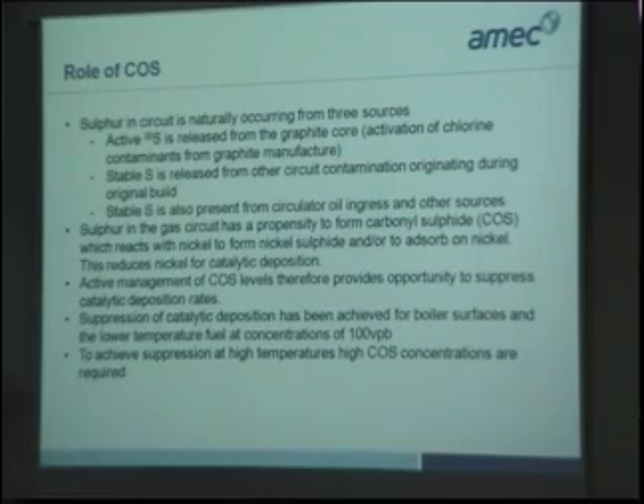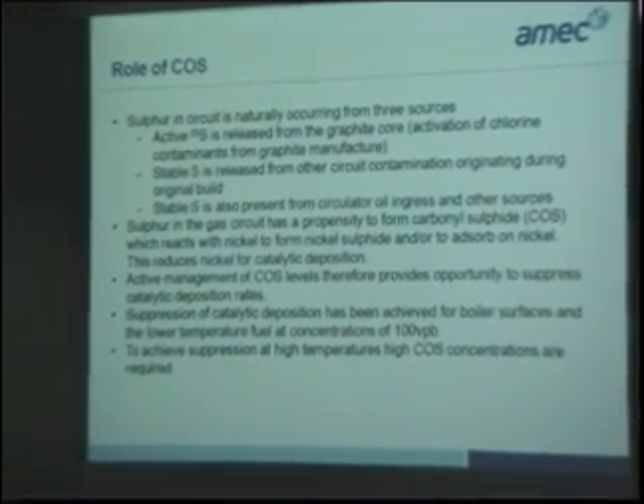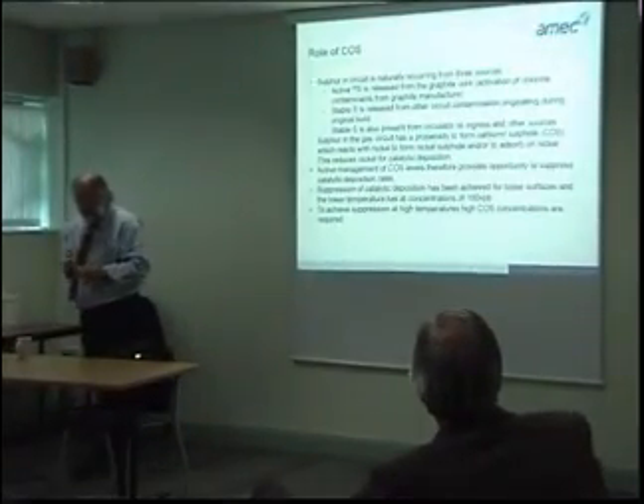And so at the moment we're adding about 100 parts per billion to reactors like Hartlepool, for example, and the safety case is being made to increase that to about 200, parts per billion I should say, to 200 parts per billion. Unfortunately, you need quite high levels of COS to suppress the deposition at high temperatures. And one of the negative things about COS is the increased S35 discharges, which, although it's only a beta emitter, it's still of concern to the Environment Agency.